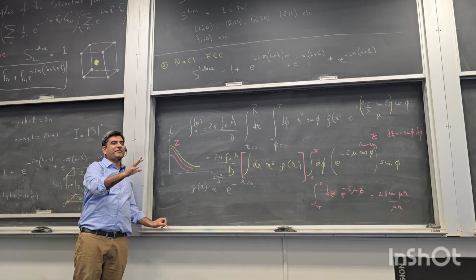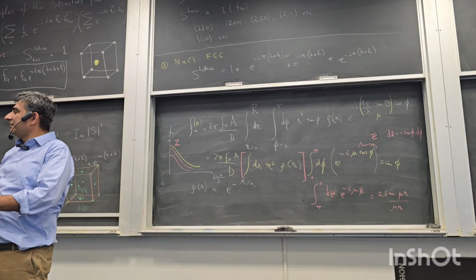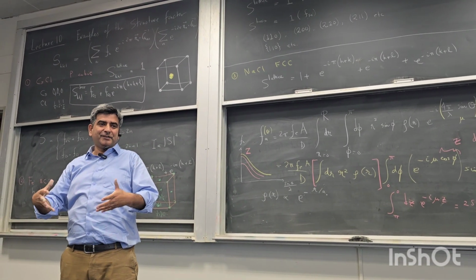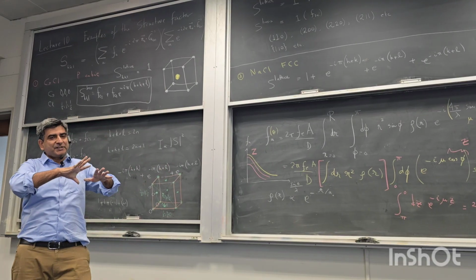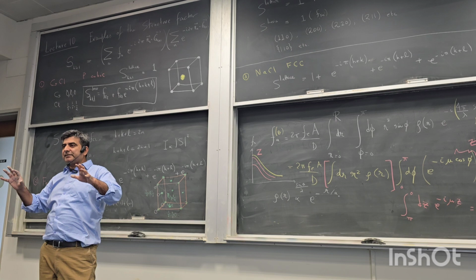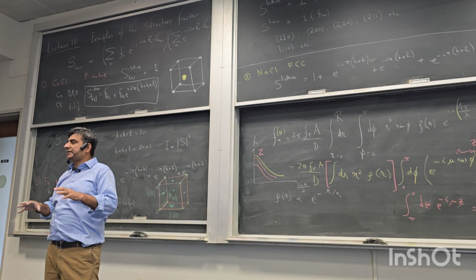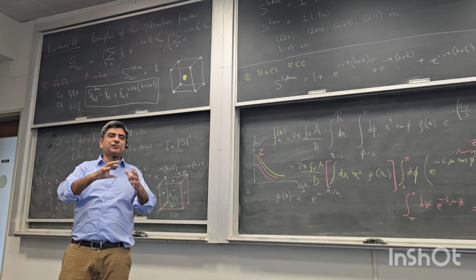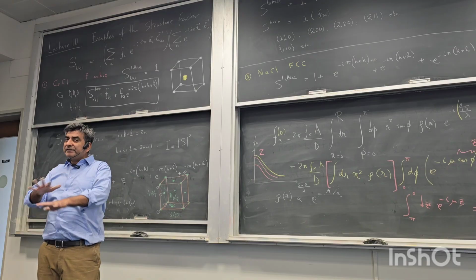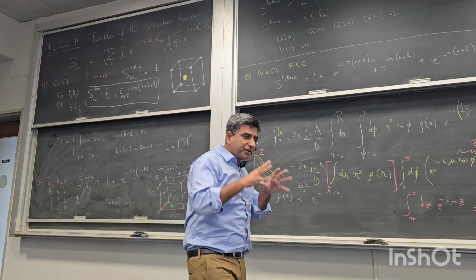But there are additional factors that control the dependence of the intensities on theta, like polarization, thermal effects, other instrumental aberrations. But this is a broad sense which tells us that even though the structure factor calculation tells us what the intensities are going to be broadly, there's an additional modulation due to the dependence of the atomic scattering factors on the angle theta. Now this finishes our discussion on diffraction theory, on the structure of crystals.